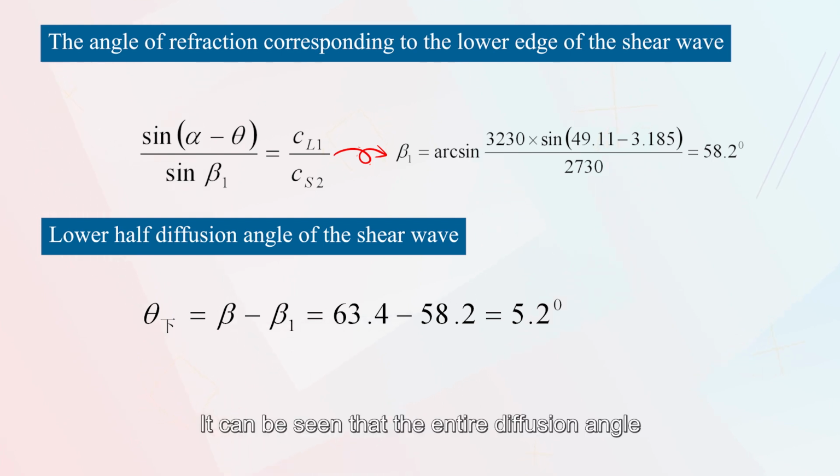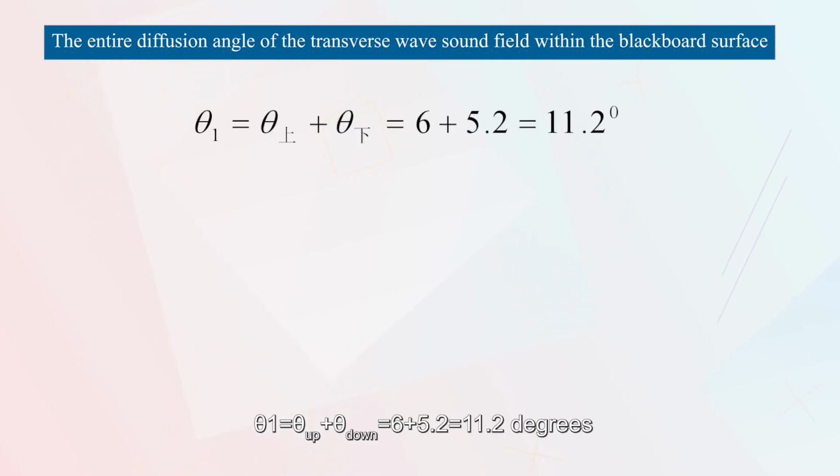It can be seen that the entire diffusion angle of the shear wave sound field in the plane shown in the figure is theta 1, equal to theta up plus theta down, which is equal to 6 plus 5.2, which is equal to 11.2 degrees.